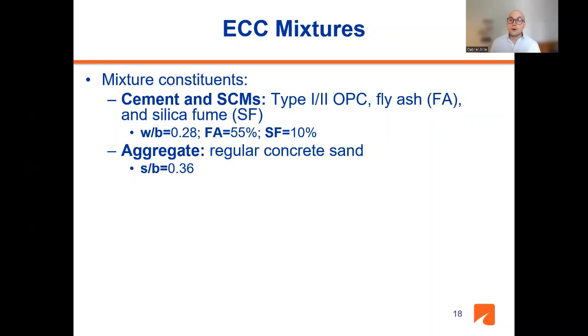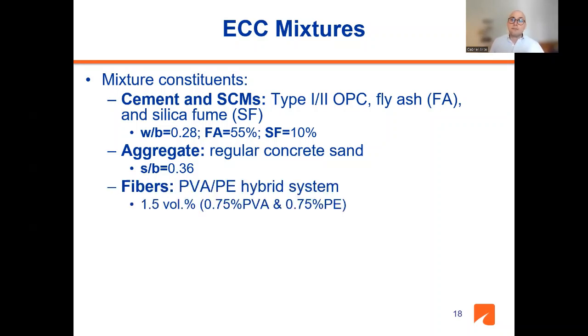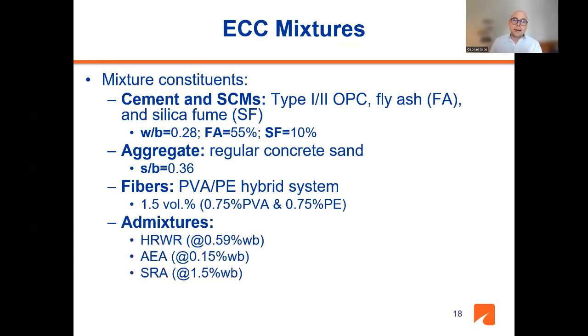And this is very important because usually for these ECCs, you want very fine particles because that helps in this pseudo-strain hardening behavior. Nonetheless, we are trying to implement materials that are readily available in Virginia. And the sand to binder ratio that we're using is 0.36, which is very normal for these ECC materials. Fibers that we're using, PVA, we're using PE, but for these particular mixtures that I'm going to show you, these are hybrid systems of PVA and PE fiber at 1.5 volume percent. That's a total volume percent of the fibers, which are distributed as 50% of that amount PVA, 50% of that amount is the PE fiber. In the mixtures we use high range water reducer, air entraining admixture, and we have also tested the use of shrinkage reducing admixture.